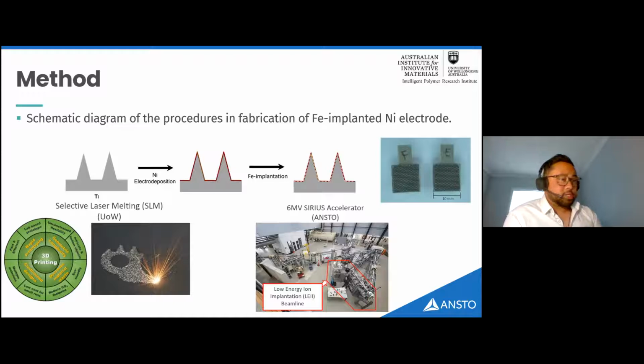So we used an additive manufacturing technique known as selective laser melting, and that uses a high-powered laser, you can see in the image down the bottom, to sequentially weld sectional areas of a designed component, allowing for the creation of complex and intricate geometries from a starting metal powder. So in this case, we designed and produced a titanium conical array consisting of 407 cones. The cone heights were about 700 microns and the base diameter about 450 microns. And then we electrode deposited nickel onto this array, about 10 microns thick. And then ion implantation was used to implant iron into that nickel layer, overall giving material modification control on both the design array architecture as well as on the implantation parameters, as Zeljko touched on earlier, to be able to control the dose and also the depth.